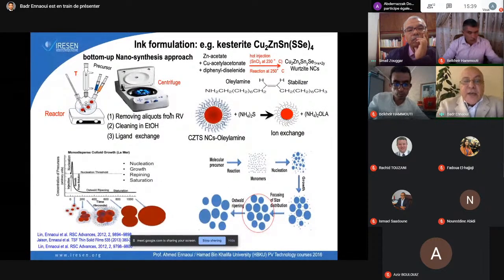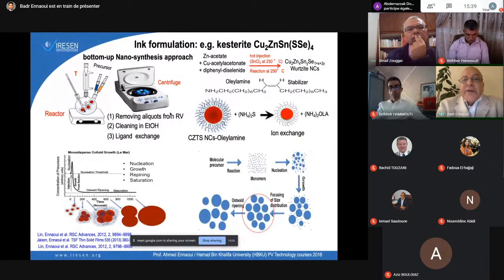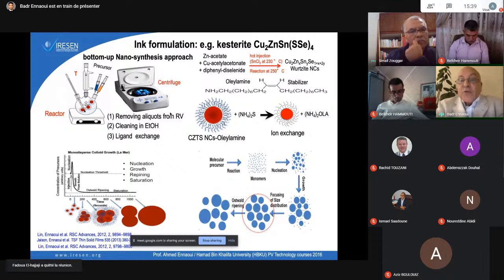For example, when you make synthesis, nanosynthesis, one of the problems is to avoid agglomeration, because you start with small particles and then they will grow and grow, and then at the end you have just what you don't need. Therefore, there are many methods with the nanosynthesis chemists now to use ligands in order to stop the nanoparticle from growing. And oleylamine is one of them.